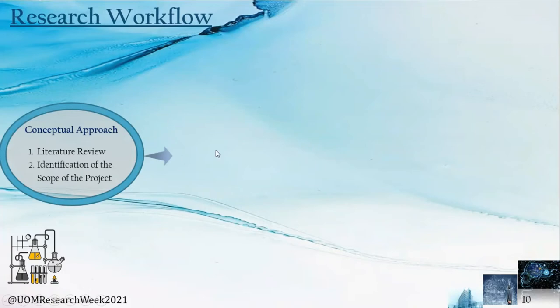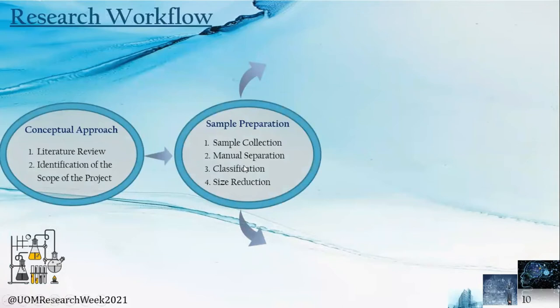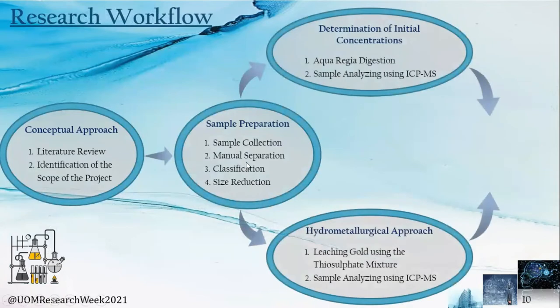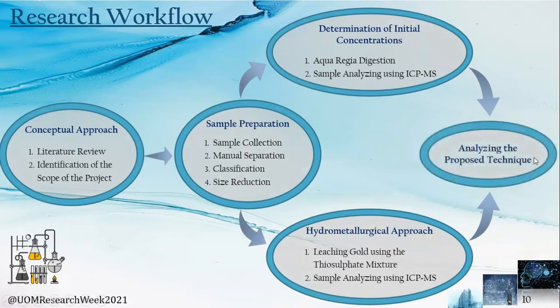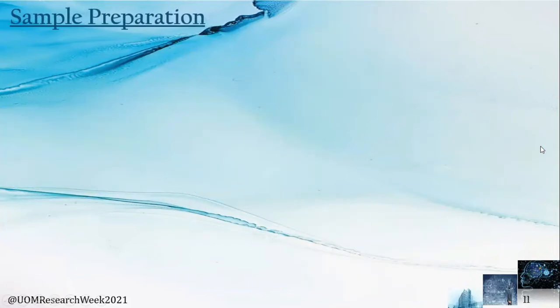After the conceptual study, sample preparation was done using several pre-processing stages. Then, the initial concentrations of metals were determined using a digestion process. For gold leaching, ammonium thiosulfate was used as a less toxic reagent. The samples were then analyzed using ICP-MS, and the proposed leaching technique was evaluated based on leaching efficiencies.